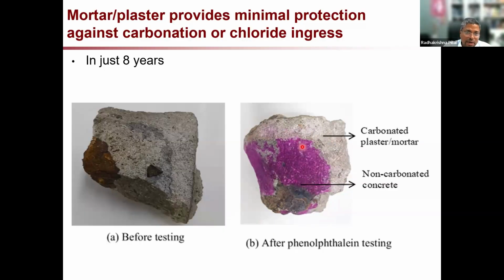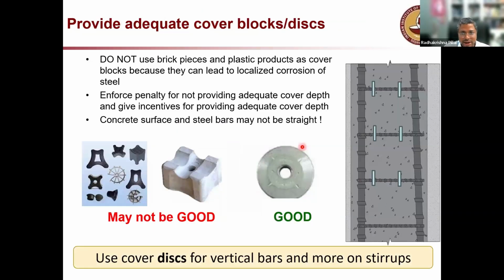So the message, what I would request you, is try to avoid plastering if at all it is possible, because then you will ensure that the concrete is of good quality. And when concrete is of good quality and adequately thick concrete cover is provided, then your structure will really last. Now, how do we ensure that this good quality cover is provided? Usually, I've seen many places where plastic cover blocks are used. My suggestion is not to use that.